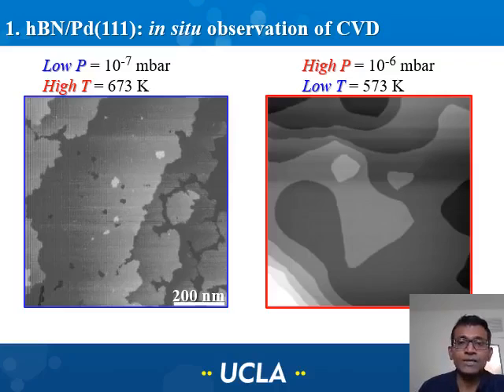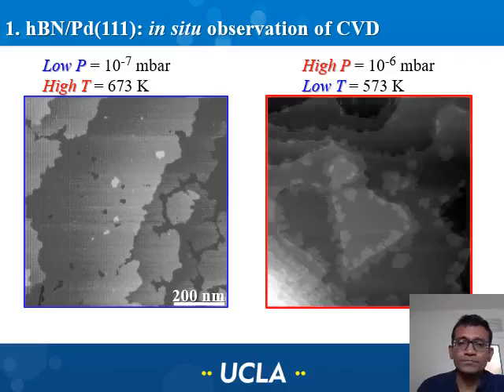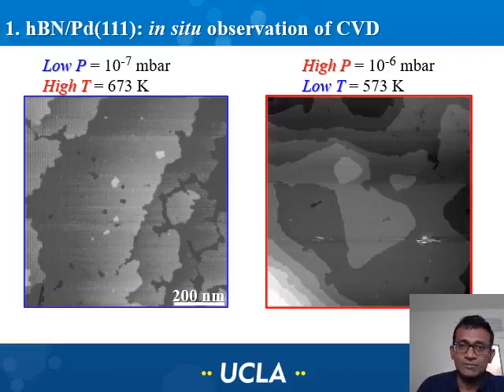growth. Now I'm going to show you a similar set of images acquired this time at higher pressure than what was used in the previous experiment and at lower temperatures. So basically we are having more deposition flux, and again we start with a bare palladium surface, and these are single atom height steps, and these are single atom high islands on clean palladium surface. And watch what happens, and we see complete monolayer coverage after a certain time. And now this is a monolayer hexagonal boron nitride covered palladium-111. And in this case, I will show you in the following slide that the deposition occurred preferentially at the step edge.